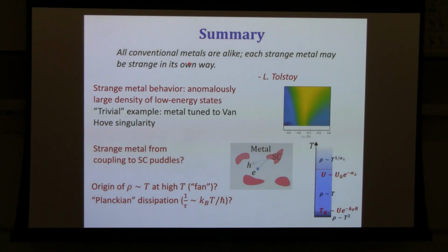Let me mention some open problems. This picture of small superconducting inclusions in a metal may work to explain the foot region, the overdoped region of the cuprates, but it kind of hides the elephant in the room. There's the fan, the linear in T resistivity that extends up to very high temperature, close to optimal doping. That theory definitely is not the right theory for that behavior. We have to assume that these two behaviors have a different origin.